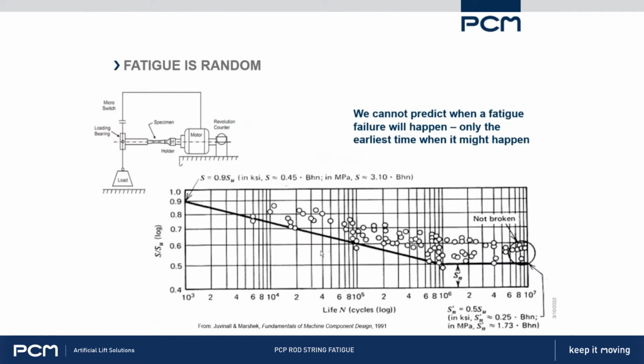And the results are plotted in a graph like this. On the vertical axis, we have stress, which is S. So high stress is up here, this one is stress divided by the ultimate stress, but it's just a measure of stress. And then on the x-axis or horizontal axis, we have N, which is the number of cycles. So this is called an SN curve. Each of these dots represents a test on this apparatus where they loaded the specimen with a certain weight to put that stress in it, and then ran it until it failed.